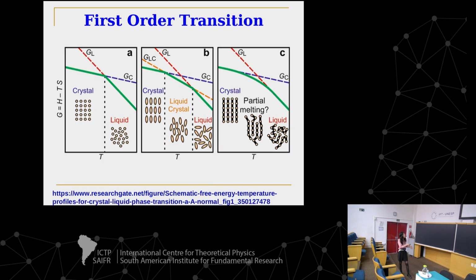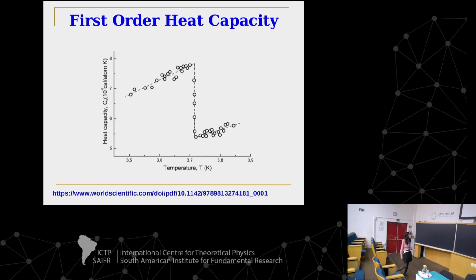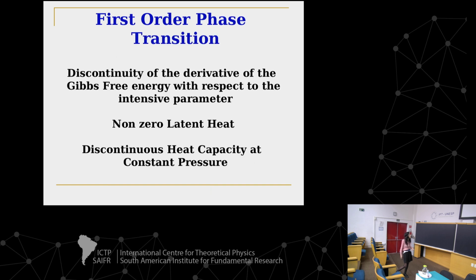And this is just to show some examples of G for other materials than what I was discussing first, the liquid-gas. So we have many transitions that are first order. You're going to have one change of slope for each one of the first order transitions that appear, if you are able to calculate the Gibbs free energy against temperature. And that's what happens with the specific heat, the second derivative of the Gibbs free energy with respect to T, which can also appear with a jump.